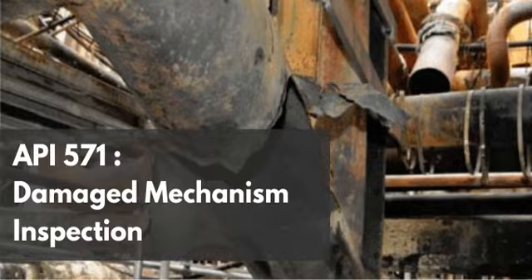But once the skin of that metal crosses that specific 1,100 degree Fahrenheit threshold, the atomic lattice of the steel physically expands and vibrates with such intense energy that the atomic doors are essentially thrown wide open. And the carbon just rushes in. Yeah, the tiny carbon atoms can now literally slip between the iron atoms and diffuse deep into the core of the material. Okay, so the doors are open, but what exactly is waiting outside to get in? What is providing all this carbon in the first place?